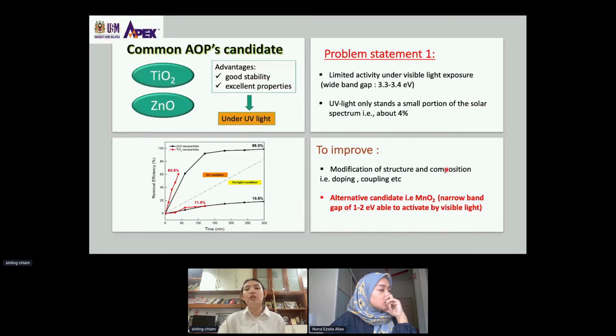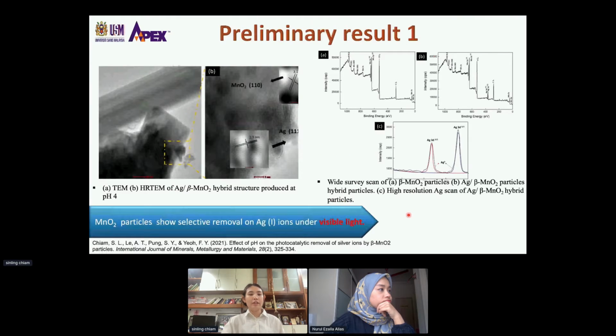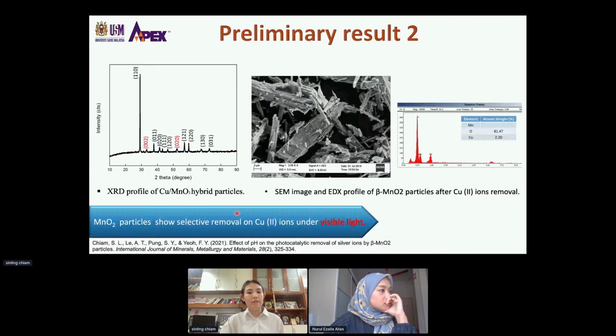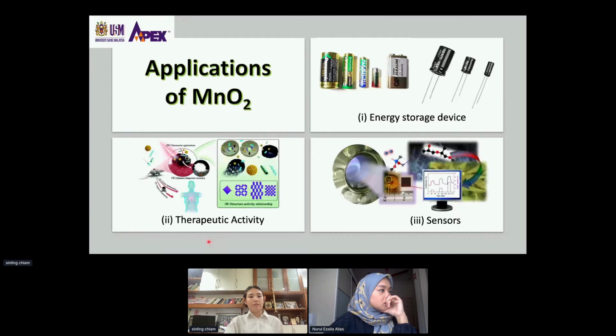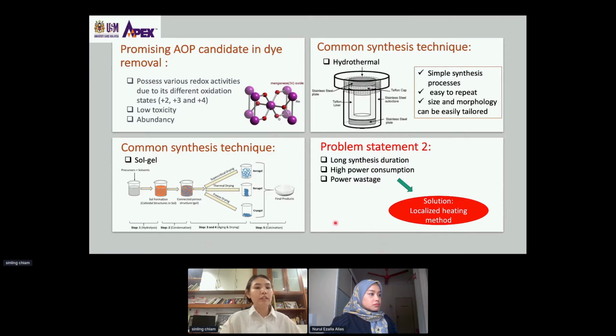Besides, as an alternative, we can use manganese oxide, which is a narrow bandgap semiconductor. The bandgap of manganese oxide is in the range of 1 to 2 electron volt, which is able to be activated by visible light. Our preliminary result shows that manganese oxide particles show selective removal of silver ion under visible light. It also shows selective removal of copper-2 ions under visible light. Besides, manganese oxide also has been widely used in energy storage devices, therapeutic activity, and sensors due to their attractive properties such as stability, relatively cheap, and safe. For dye removal, manganese oxide possesses various redox activities, low toxicity, and abundance. Those make it attractive in wastewater treatment.